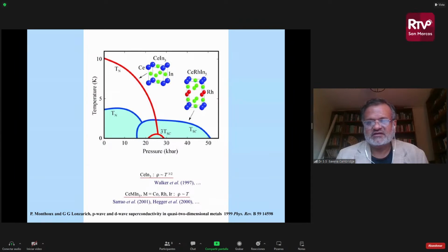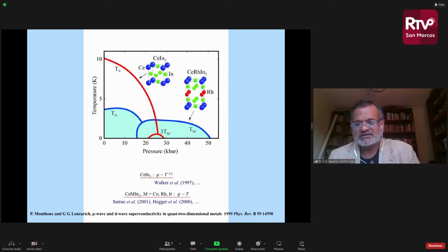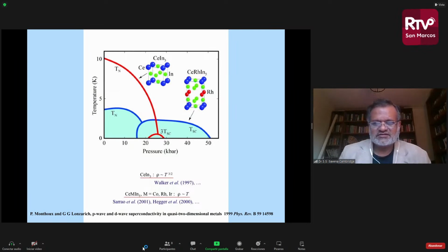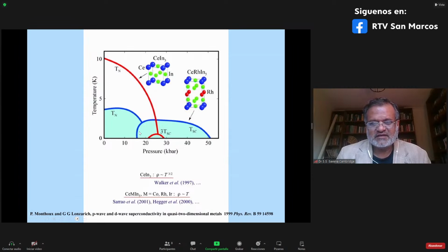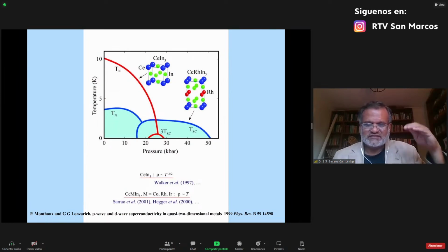not necessarily only in terms of having a layered structure, but also in terms of interactions, meaning that if you look at the Fermi surface of this material, this one with a layer, you'll find that it becomes more and more cylindrical. So the 2D characteristics start to become more apparent in electronic properties as well. And you see an interesting comparison here: you take this material, which is more 2D, and you see the superconductivity emerging, and you'll actually find that it's a decade higher, so 10 times more. And you're able to enhance superconductivity in this, going from 3D to 2D.